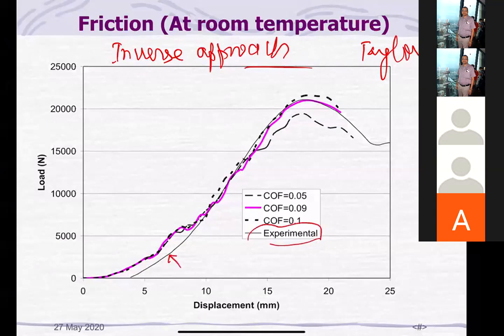Experimentally, we can calculate the load displacement. Now in the simulation, I am keeping all the parameters the same and varying only the friction. Only friction I'm varying. So at 0.09, this graph overlaps almost with the experimental curve. So I will say at room temperature, mu is equal to 0.09. And for the rest of the studies, I will use 0.09 coefficient of friction only.